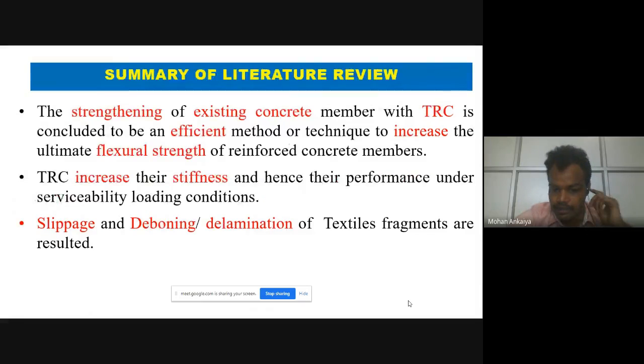As I said, two major defects have arisen. One is slippage and debonding of textile fragments, and under any high load, the increase in stiffness has been achieved with the TRC compared with FRP. Slippage or debonding is when we bond with the beam surface and it is acted on by the load, the fibers may pull out from the cementitious layer. So it is known as slippage, debonding or delamination of the textile fiber.